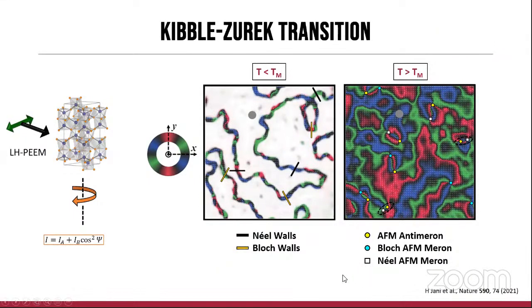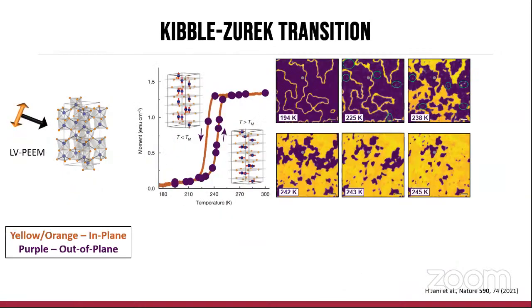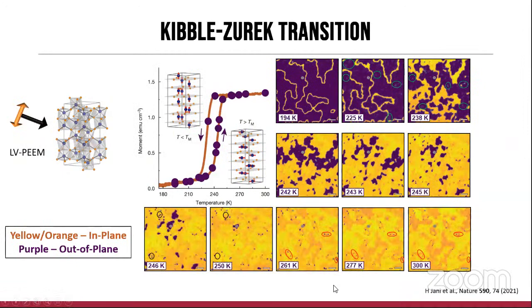Sorry, excuse me, actually it's the previous slide in the image. This image in the 300 Kelvin, right? You see this, you're measuring, in some sense, the out-of-plane Néel order, right, in this image? No. We are able to look at various orientations of the Néel order. The polarization of the X-ray is vertical, but we can actually distinguish the in-plane from the out-of-plane because they produce different contrasts when you use a vertically polarized X-ray.